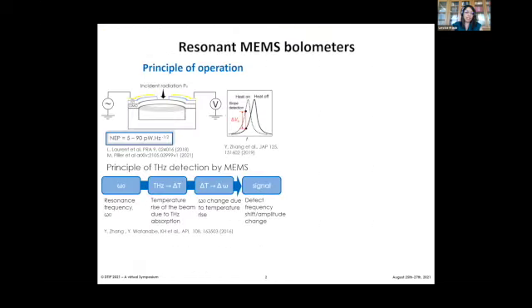substrates. So the idea here is to evaluate PZT for the development of innovative devices such as these resonant MEMS bolometers. So the bolometers, they are thermal radiation detectors. So in this case, when we have an incident radiation here, the temperature of the sensitive material will increase. And we can detect this increase in temperature via the top PZT that's going to actuate, and also detect on the other side as a variation in the voltage. So the idea is that the LSMO is absorbent in the infrared region. So when we illuminate this sample with infrared radiation, it will induce the temperature rise of the sensitive area, as we can see here. And this structure has to be thermally insulated so we can have a higher sensitivity.